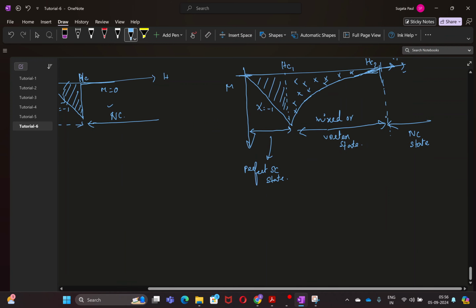So if you think about it, between Hc1 and Hc2 is a regime where it is not in a perfect superconducting state, nor is it in a perfectly normal conductor state. It is a mixture of superconducting and normal conducting states. You can think of it as a superconducting background, but inside that background there are certain small parts where the flux can enter, and those are called vortices, which are small regimes of normal conductor inside a superconducting background.